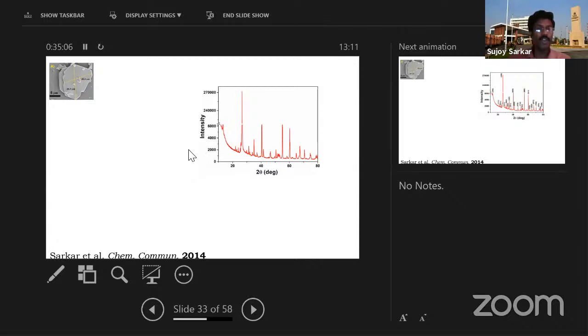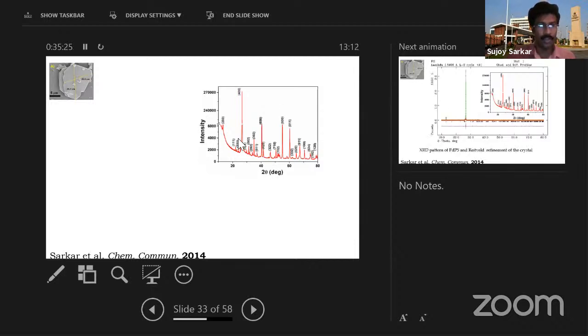How did it come out? We looked at the literature. This material was synthesized only in 1972. After that, nobody actually worked on this material. In 1972, they did a single crystal study, and from there they found out what the peaks are. So we found that these are the peaks. But their preparation method and our preparation method are different.